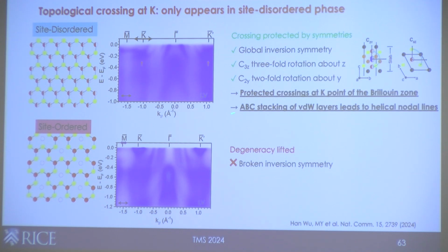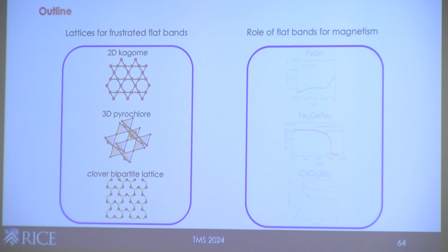And then we have ABC stacking of the van der Waals layers. This will lead to helical nodal lines around the K point as you go in the kz direction. So these are topologically distinct situations. For the bottom one, where the inversion symmetry is broken, you actually see the lifted degeneracy at the K point. But I just thought vacancy order is a very interesting way to tune symmetries in bulk materials and also give you flat bands.